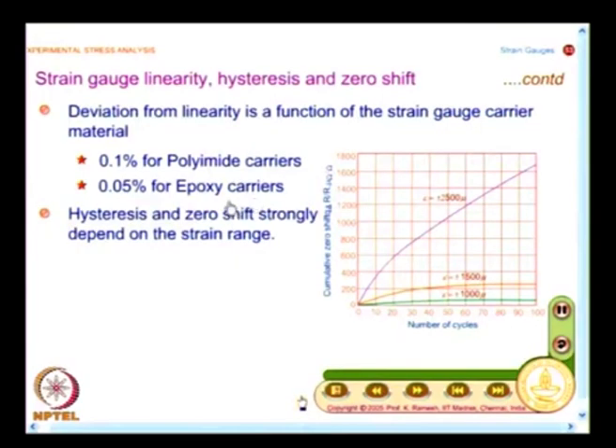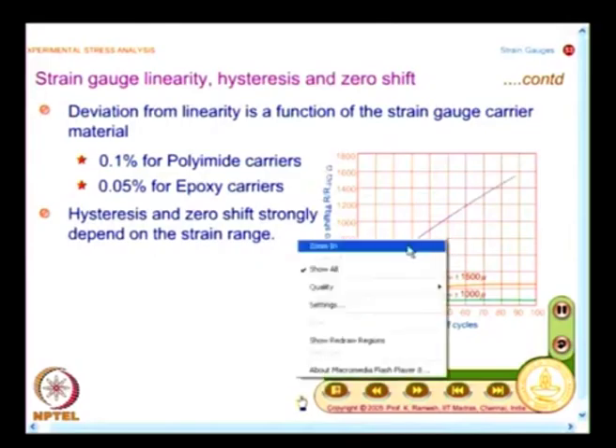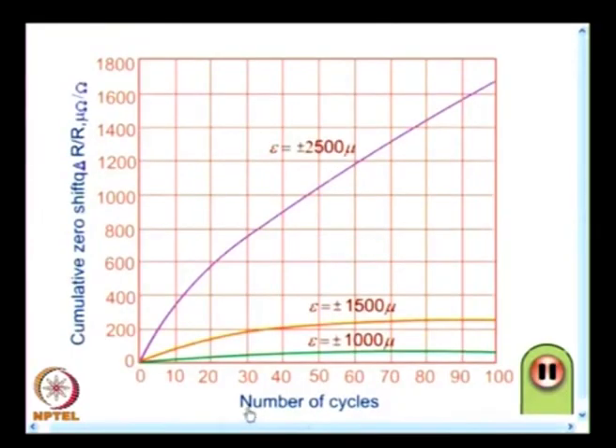And we have also looked at strain level plays a role, and what is observed is hysteresis and zero shift strongly depend on the strain range, and that is what is illustrated in this graph. You can have a look at it. So, what I have here is on the x axis I have number of cycles, and the y axis you have cumulative zero shift, and the graph is plotted for a strain range of plus or minus 1000 microstrain, then another graph for 1500 microstrain, and the third graph for plus or minus 2500 microstrain.